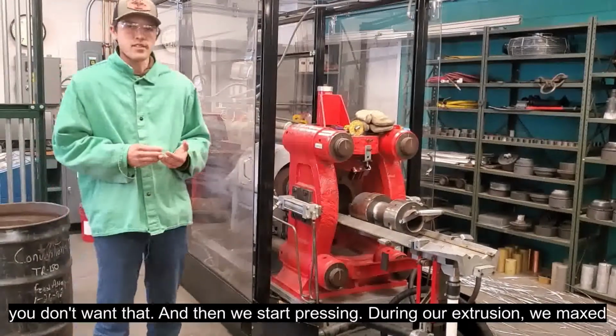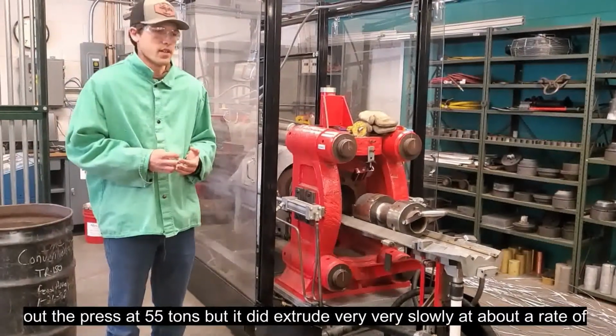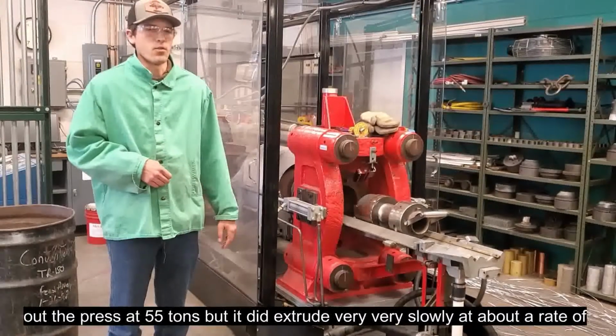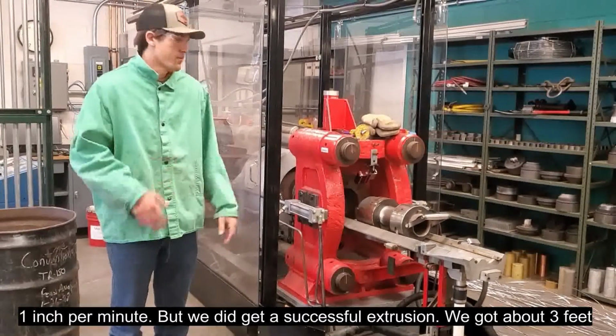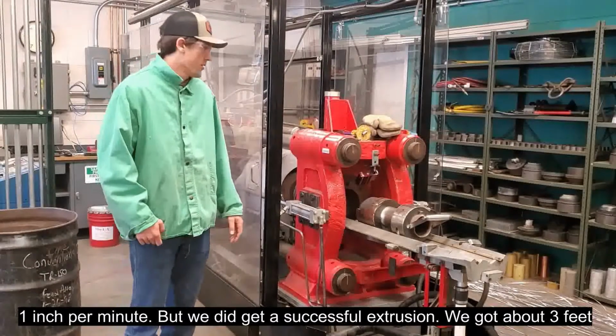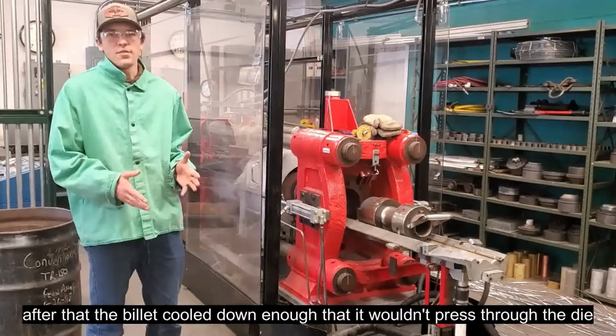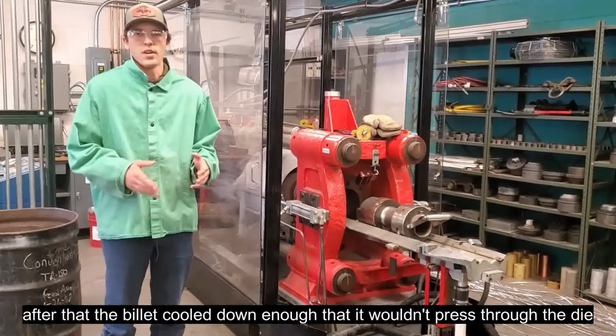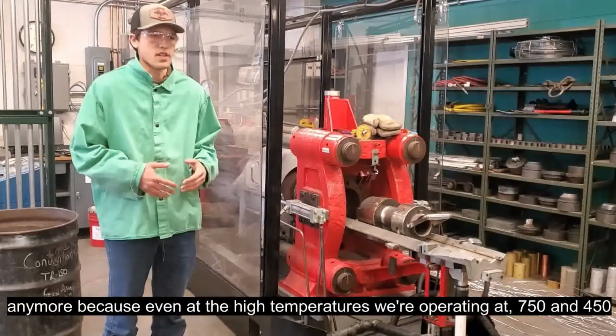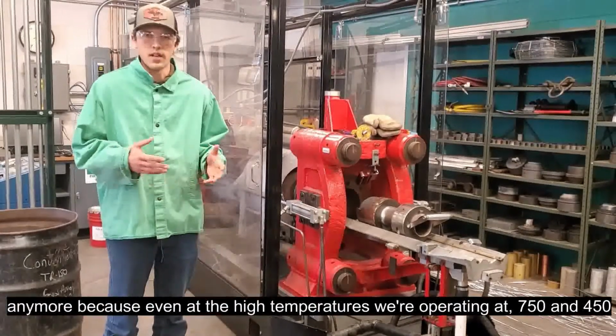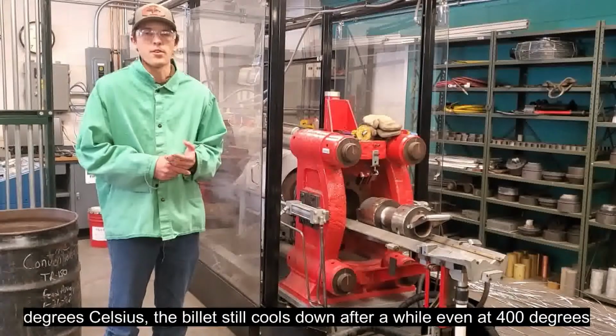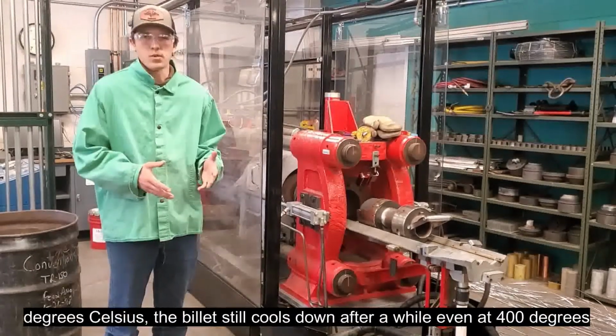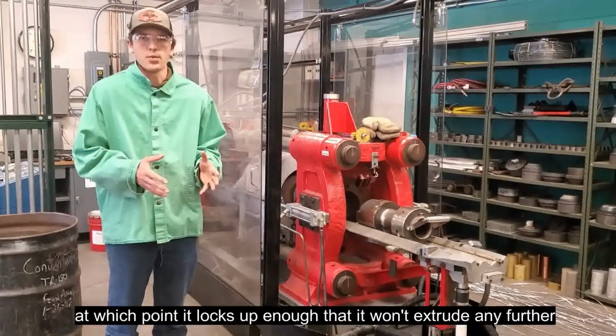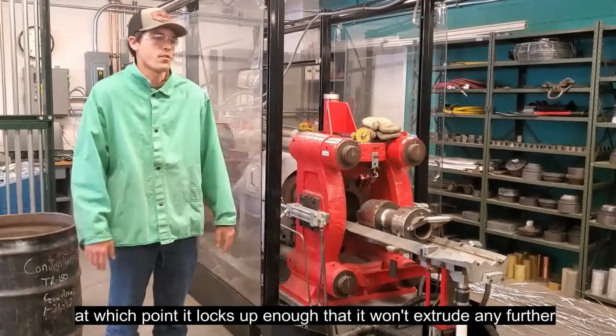During our extrusion, we maxed out the press at 55 tons, but it did extrude very, very slowly, at a rate of about 1 inch per minute. But we did get a successful extrusion. We got about 3 feet. After that, the billet cooled down enough that it wouldn't press through the die anymore, because even at the high temperatures we're operating at, 750 and 450 degrees Celsius, the billet still cools down after a while, even to 400 degrees, at which point it locks up enough that it won't extrude any further.